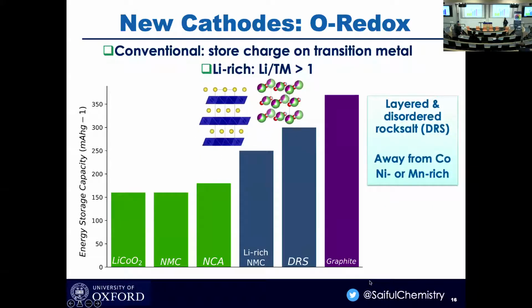So these lithium-rich materials are twofold. One is a layered oxide, similar in structure to the conventional, and the other is the rock salt structure. Rock salt structure we're all familiar with, is something that we have in our kitchen, good old sodium chloride, the stuff you sprinkle on your chips or pasta, or in my case, before a tequila shot. The disordered rock salts have a low cobalt content, they're largely nickel or manganese rich. We can see the energy density is increasing, in one case nearly doubling that of conventional lithium cobalt oxide.